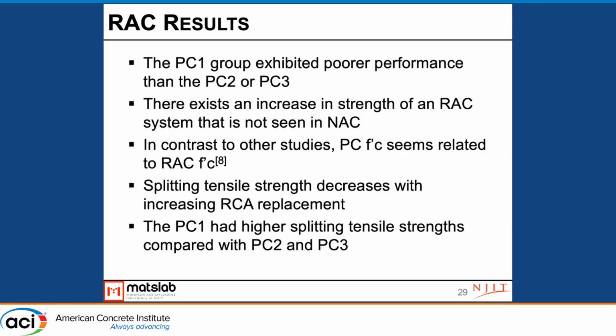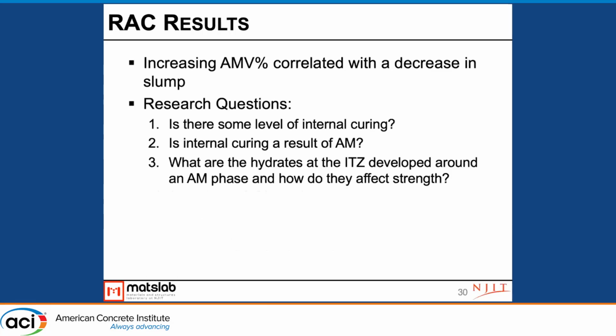Three minutes left. Okay, just some findings. The PC1 group exhibited poorer performance than the PC2 or PC3. There exists an increase in strength of an RCA system that is not seen in a natural aggregate concrete system. And then, and this is really important, in contrast to some other studies, there seems to be some effect of the parent concrete strength on the actual recycled aggregate concrete system. Most people look at it in terms of adhered mortar, but there seems to be some effect of the parent concrete strength. Splitting tensile strength decreases with increasing RCA replacement, and the PC1 had higher splitting tensile strengths.